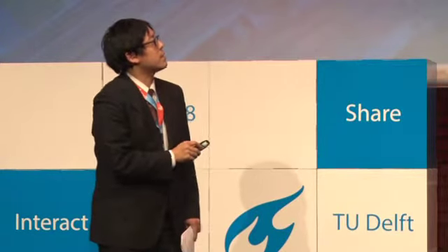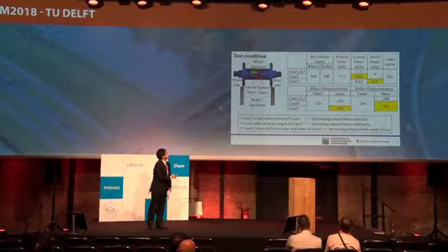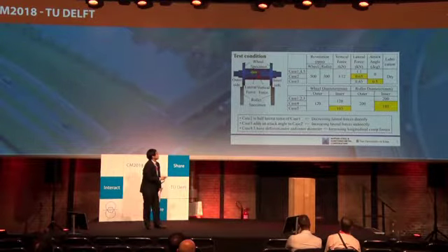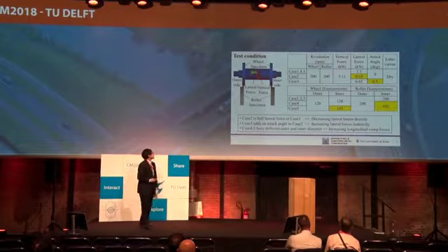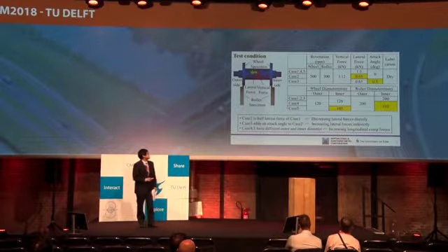To the wheel specimen, vertical force and lateral force are applied, and the rollers have attack angles. We have 5 conditions, and we changed vertical force, lateral force, attack angles, and wheel and roller diameter. Case 2 is half the lateral force of case 1. It is aimed at decreasing lateral forces directly.